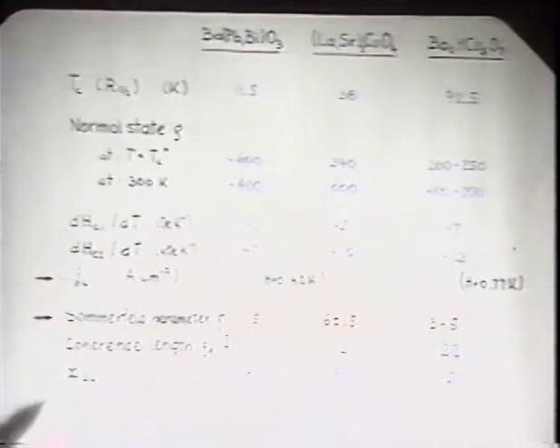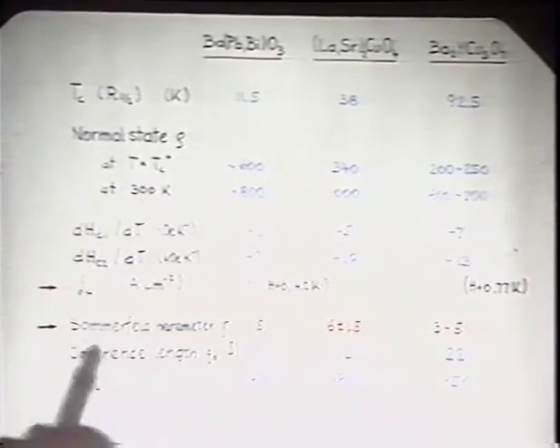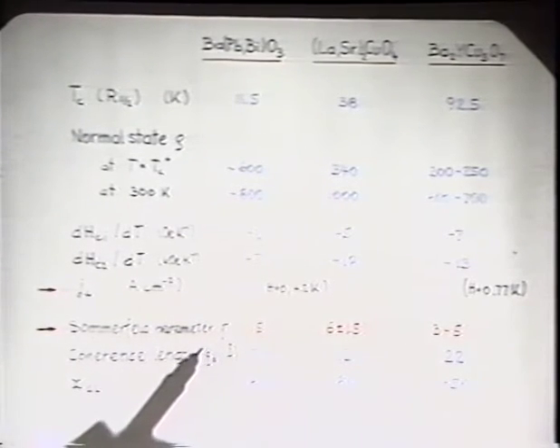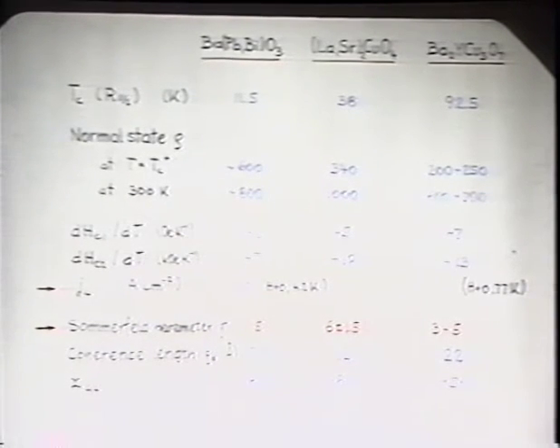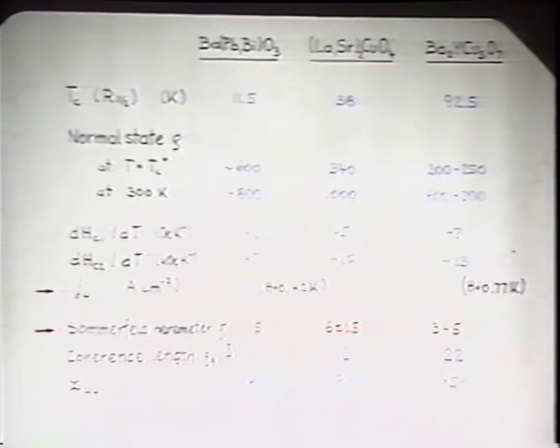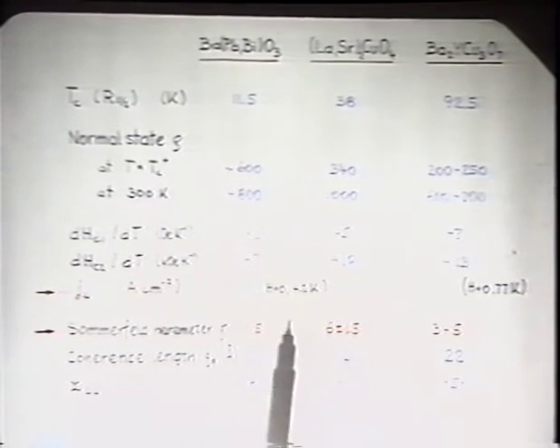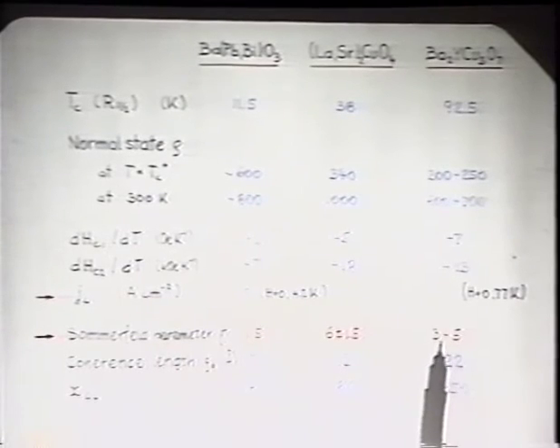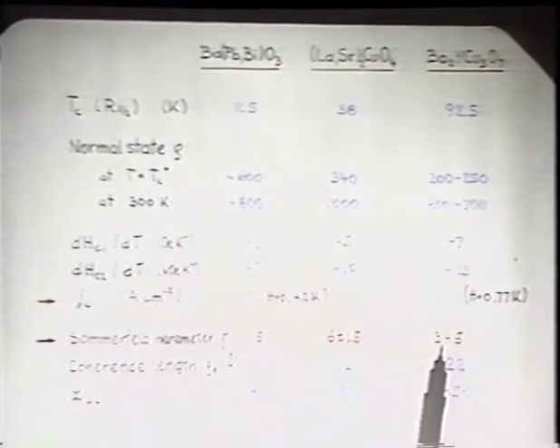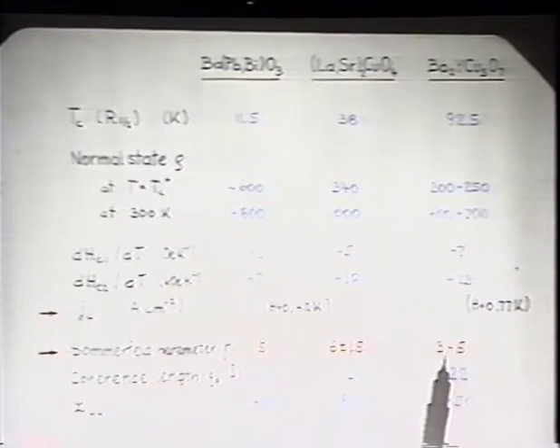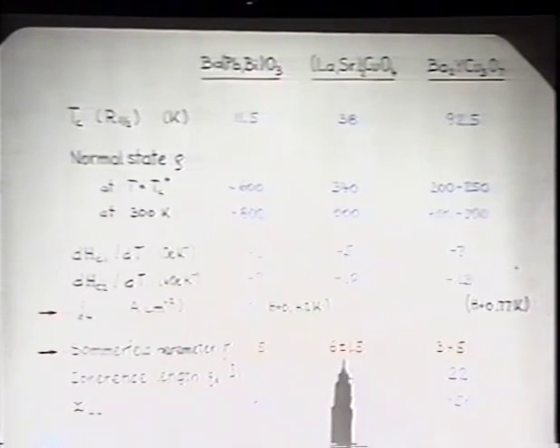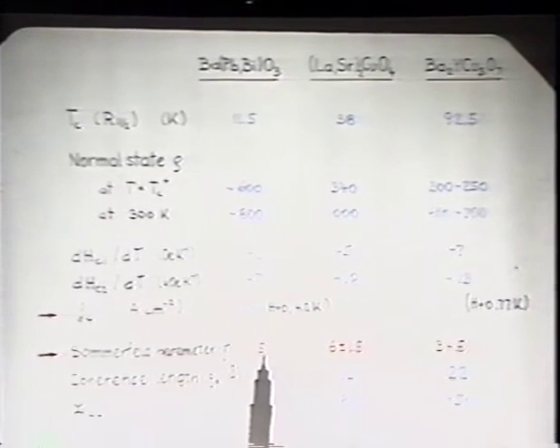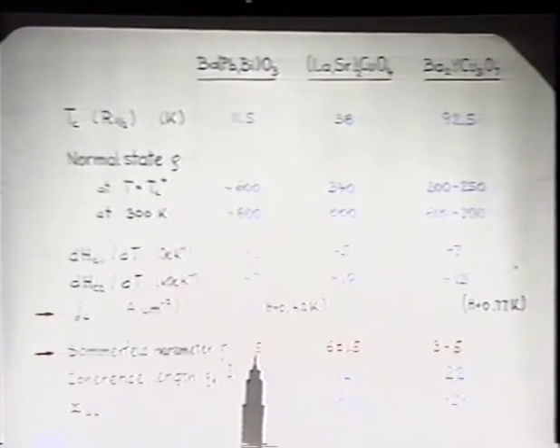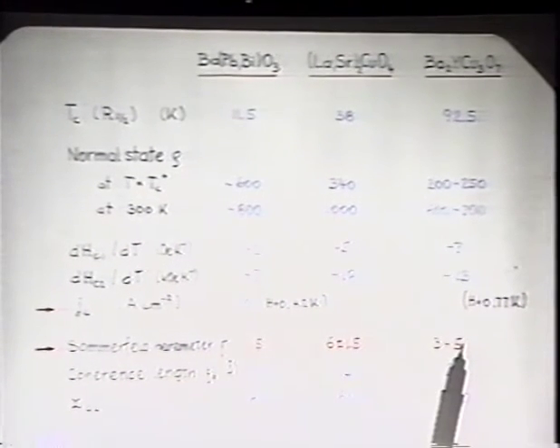Now, there are two points which I'd like to point out. One is the Sommerfeld parameter, which we have derived from various measurements independently. They all give consistent results, and I was somewhat surprised seeing the large value of 25. We found for the barium yttrium copper oxide a gamma value, in the usual units of millijoules per mole Kelvin squared, of about 3 to 5 only, which is even lower than the one in lanthanum strontium and is only slightly higher than it is in barium lead bismuth oxide. So these are very low density of states at the Fermi level compared to others. I will come back to this point explicitly in the next view graph.